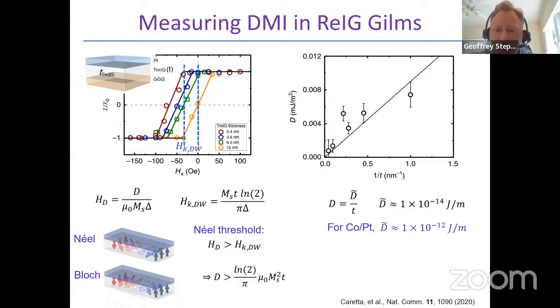So for cobalt platinum, MS is quite large. And MS squared is then also very large, which means you need a lot of DMI to stabilize a Néel wall. For these garnets, MS is 1 or 2 orders of magnitude or even more smaller than it is for metals. Therefore, the amount of DMI that is required to stabilize a Néel wall is also much smaller. So because of the low MS in these materials, even though there's a relatively low DMI, that also turns out to have the opposite chirality to that of a cobalt platinum interface, it's sufficient to stabilize chiral textures in these kinds of films.